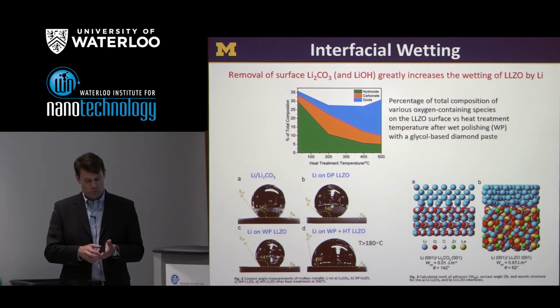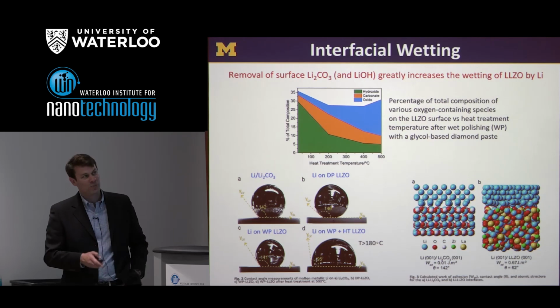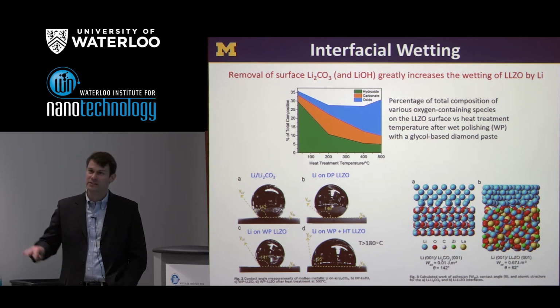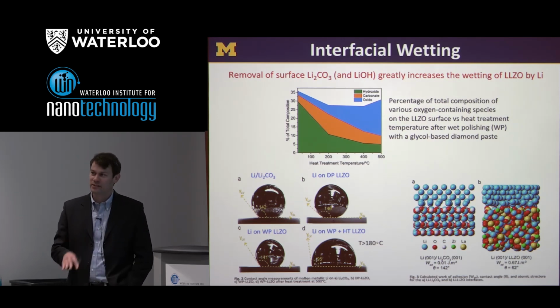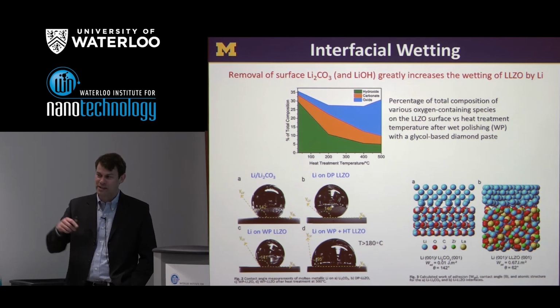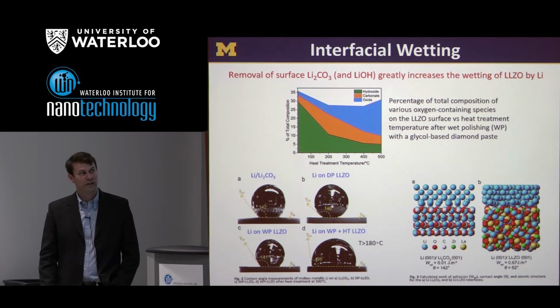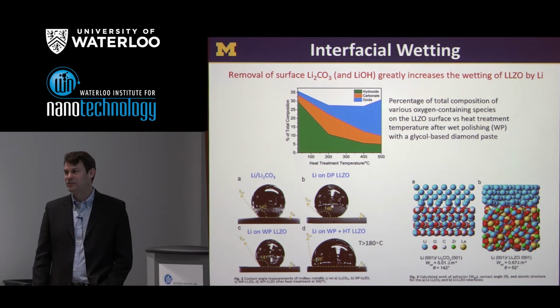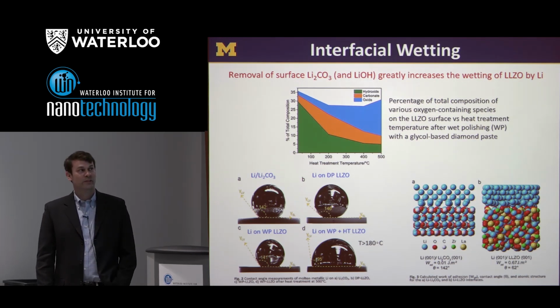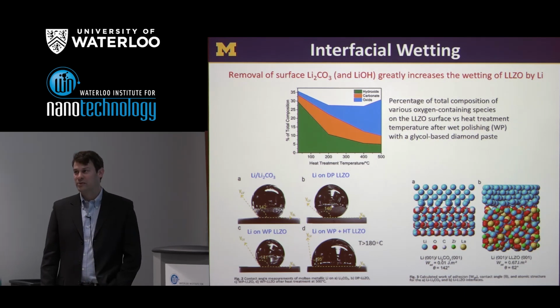One reason why I think that this wet polishing works better is that it probably prevents some reaction with the atmosphere due to the presence of this liquid phase. Of course, that liquid phase is doing other things, like maybe protonating the LLZO. But this polishing is all done outside of the glove box, and then the heating is done inside a glove box.